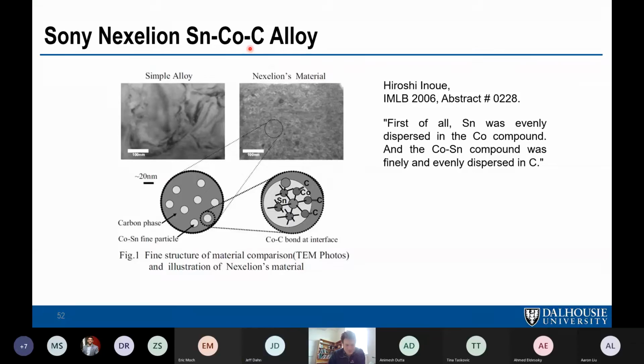This is tin cobalt carbon, and it was introduced by Sony, and then they took it off the market. It was a very nice material, but I suppose it's really costly. You've got cobalt here and tin, which we showed is much more expensive than silicon, and cobalt's expensive too. This was made by ball milling these phases together. First, they made the cobalt tin alloy, and then it was ball milled to disperse it in carbon to make this completely amorphous alloy.